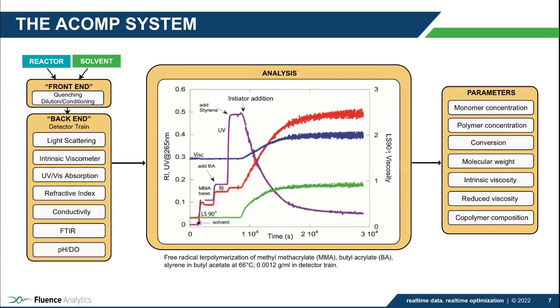Now going into more details on the technical aspects of ACOMP. The system basically comprises what we call the front end, where the reactor is mounted with a recirculation loop to ensure that the reactor content extracted is representative of what's actually happening inside the reactor. An extraction pump is attached to it to continuously extract small amounts of reactor contents that then go through whatever conditioning is necessary, such as diluting, quenching, or breaking emulsions. Once it reaches analytical grade, it moves into the detector train, the backend, that can be customized depending on the